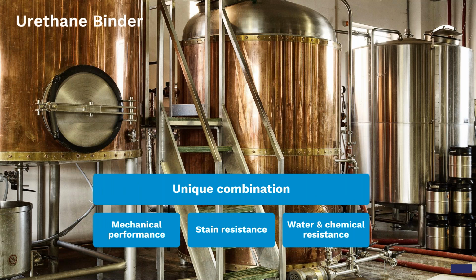So with the pre-mixed urethane, there is that urethane binder, and there is a unique combination with that, and that is the mechanical performance, stain resistance, and chemical resistance because of that urethane binder. It allows you to have a high performance resin system as they bond together to get these benefits that you see on the screen. So the mechanical performance, the stain resistance, and the water and chemical resistance really comes from the strong binding of the molecules in that urethane binder.